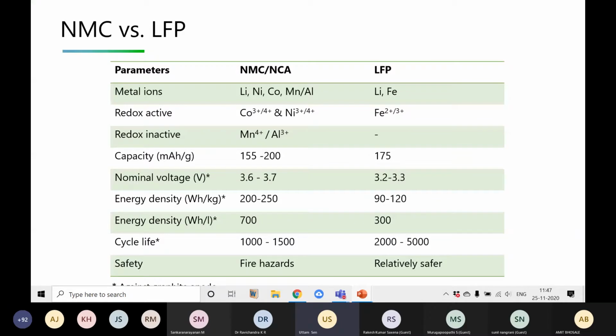To stabilize this nickel and cobalt, if we add more amount of nickel, the crystal is not stable. To stabilize this, we have to add manganese or aluminum. If we add manganese, then the material is called NMC. If we add aluminum to stabilize the structure, then it's called NCA, lithium cobalt oxide. But manganese and aluminum are not active, so they are only helping to stabilize the structure.